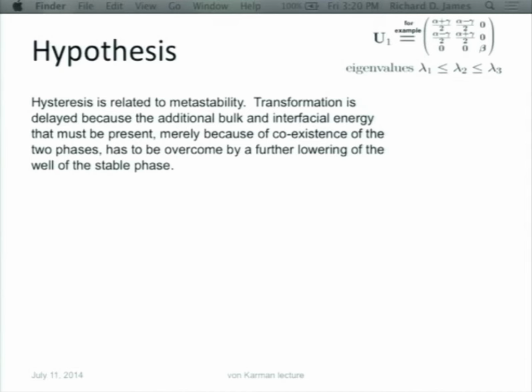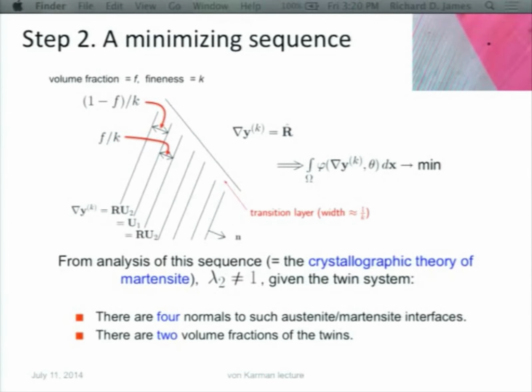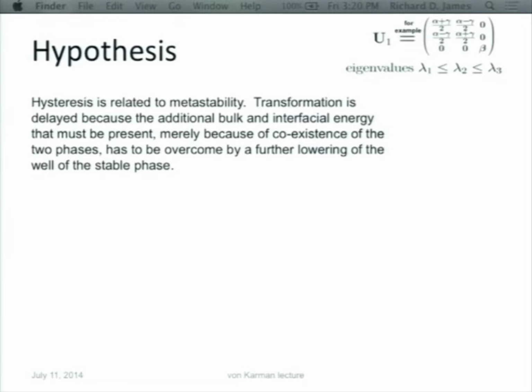So it became a little clear a few years ago that hysteresis should be related to this energy stored in this interface that is due to the competition between bulk and interfacial energy. And you can imagine you have a crystal which is all austenite, and now you want to introduce a little bit of martensite. So there's a lower energy well for martensite, so you put some material in martensite, but as soon as you do, you're forced into having these interfaces, and therefore the additional energy, that's just because austenite is sitting next to martensite. Okay? So transformation is delayed because the additional bulk and interfacial energy that must be present merely because of the coexistence of the two phases has to be overcome by a further lowering of the well of the stable phase.